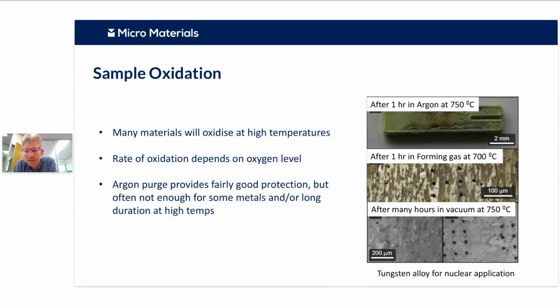So this is a slide from Oxford University, and what you can see on the right there from a nuclear project is that they were trying to test tungsten for this, similar to the application Hannah described in fusion reactors. And there they were looking at the surface of the tungsten after being exposed to an hour in argon at 750 or an hour in forming gas, even at slightly lower temperature. And what you can see there essentially is that after an hour in argon, you get a sort of greeny tungsten oxide all over the surface. It's relatively untestable to understand the effect of ion irradiation and things like that.